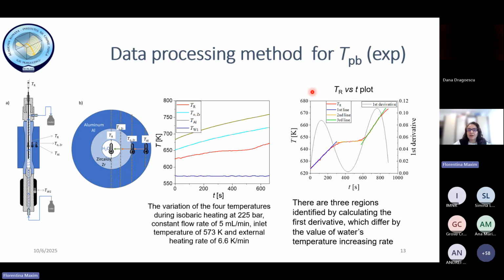we determined the temperature of the pseudo-boiling transition by experiments. We analyze practically the water temperature profile inside the reactor by analyzing the temperature variation with the time of the experiment.